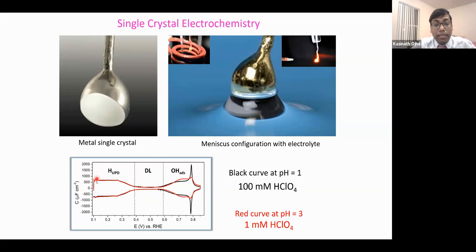I'll come to that in between. But if you do not get 111, you also don't get those peaks. This peak intensity tells you how accurate your surface is. Generally it has to be more than about three times this HUPD charge. Let's say the HUPD charge is 700 or 750, and those go to 2000, this kind of thing.